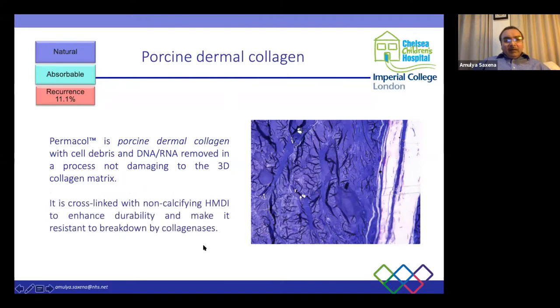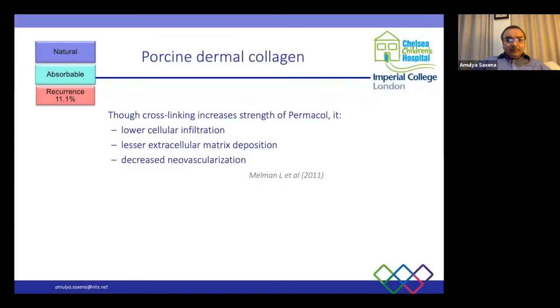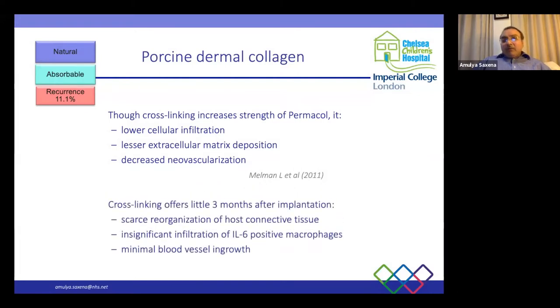There's another problem: this material is cross-linked with non-calcifying HMDI, and once you have a cross-linked material, it's so thick, it does not allow tissue integration, does not allow cells to penetrate into it easily. So cross-linking of Permacol allows lower cellular infiltration, lesser extracellular matrix deposition, and decreased neovascularization. And that's the reason for the main failure of Permacol. The cross-linking offers very little advantages after 3 months of implantation, scarce reorganization of the host connective tissue, insignificant infiltration of IL-6 positive macrophages, and minimal blood vessel ingrowth.